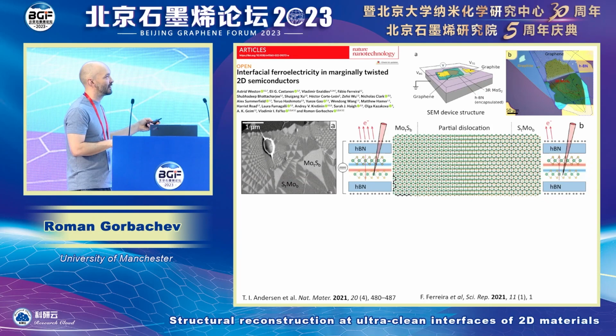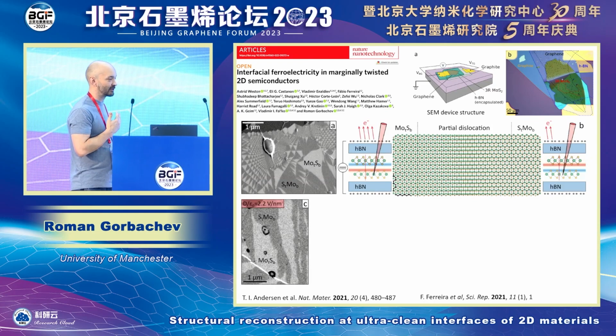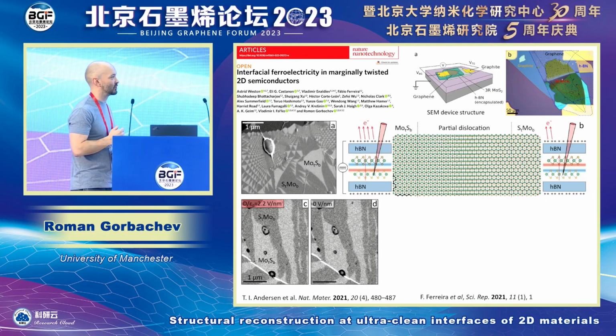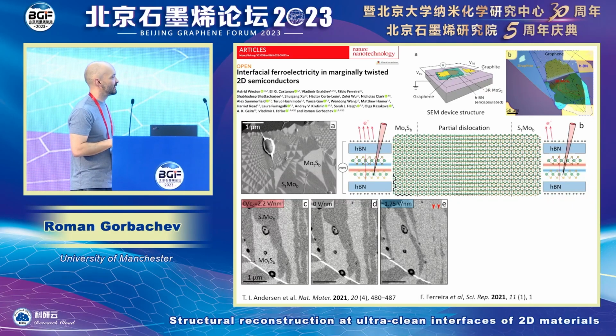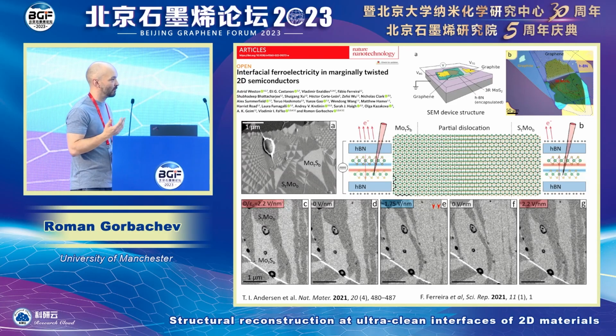So half of these domains will be polarized up, and the other half of these domains will be polarized down. Now, if you apply an external electric field and you monitor this domain map with electron microscopy, just like I showed before, you can see that as you apply the field, the dark domains shrink, and then if you reverse the electric field, they expand, and you have a hysteresis. So in terms of classical definition, this is normal ferroelectricity. However, it is now sliding type.